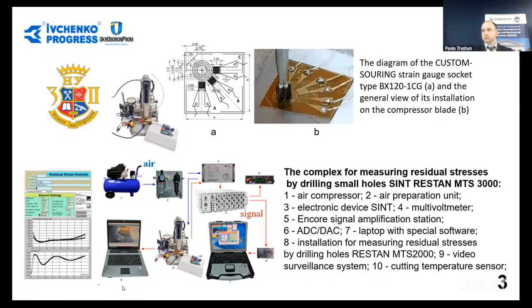The strain gauge sockets were attached to the suction side of the blade airfoils, and then the high-speed drilling was performed with simultaneous recording of surface deformation in 3 directions and simultaneous calculation of the in-plane stress state components. The stepwise drill feed with a 10 micrometer increment allowed us to study the distribution of residual stresses in the surface layer to a depth of up to 200 micrometers.